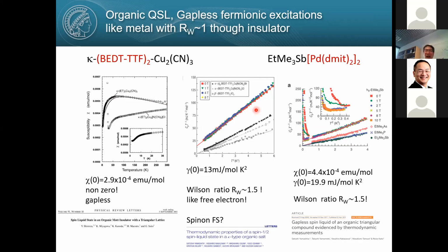Now, how about elementary excitation? So from those we confirm absence of magnetic ordering. It's likely a quantum spin liquid. Then let's discuss elementary excitation. And as you see, there is a finite susceptibility at the T equals 0 limit. So there seems to be a gapless excitation. Or if you take a look at the specific heat divided by temperature as a function of T squared, the T equals 0 limit gives rise to a finite intercept.